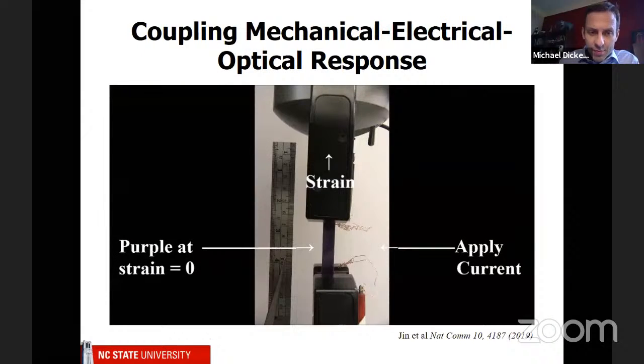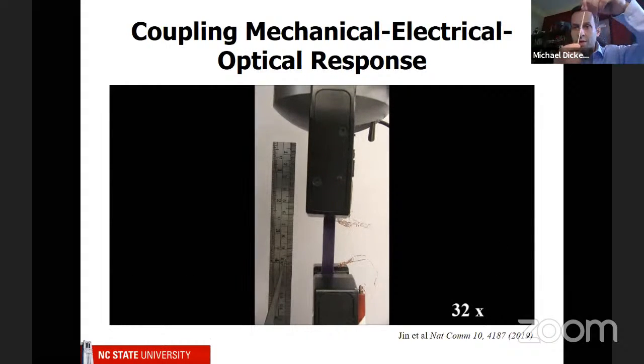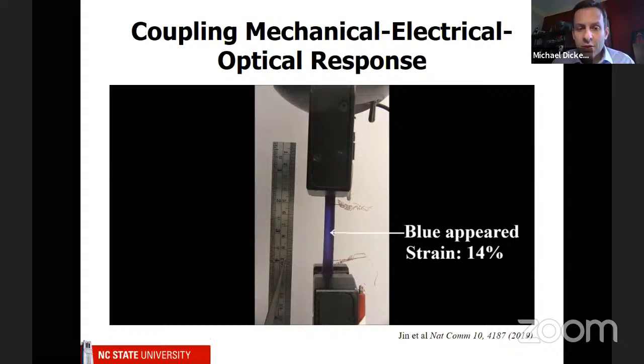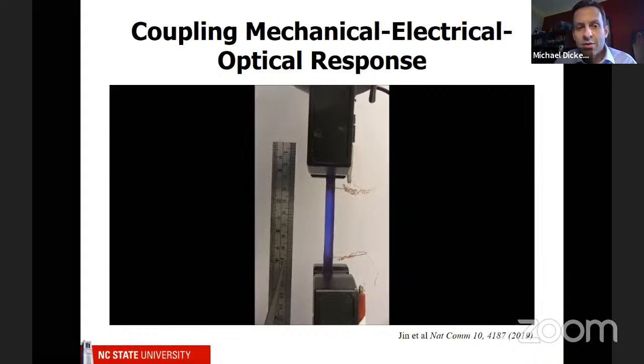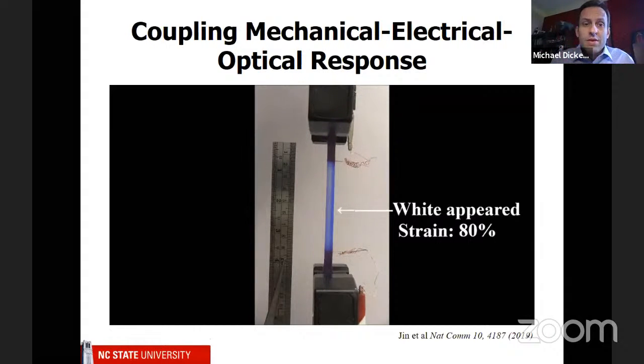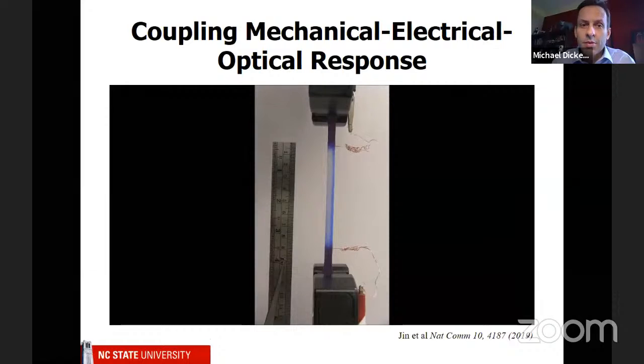So this is the same material. It's purple. It's a little bit difficult to see, but there's a liquid metal wire, a single wire that goes straight through this material. And we run constant current, and the current is not enough to cause color change. So you'll see that initially it's purple. Then when we start stretching it, we're going to make that wire longer, just like this rubber band. When you make it longer and narrower, the resistance goes up. And so you start seeing color as a result of mechanical stress. And so this is interesting because it basically couples mechanical effects with electrical effects and optical.